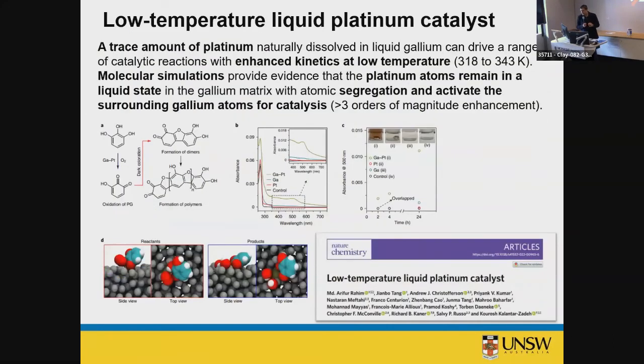And the last one is, I just published a few days ago. I just wanted to say that even the smallest amount of impurity that you add to the core can change everything very significantly. Here we're talking about 0.0001% platinum. They added it to the liquid metal, and suddenly the reactivity of this gallium metal went from 1 to 10 to the power of 3, 1,000 times, just by adding this metal. Just that much platinum to the core. You know, platinum is expensive, of course. If we can reduce the usage of platinum, it's a big achievement. If we can have the same reactivity of platinum, or even more than the reactivity of solid platinum at room temperature, it is an extraordinary achievement.